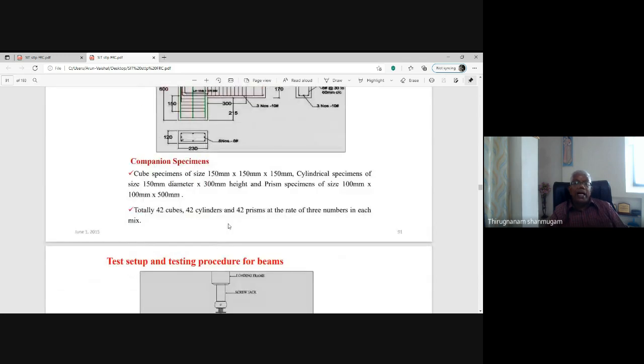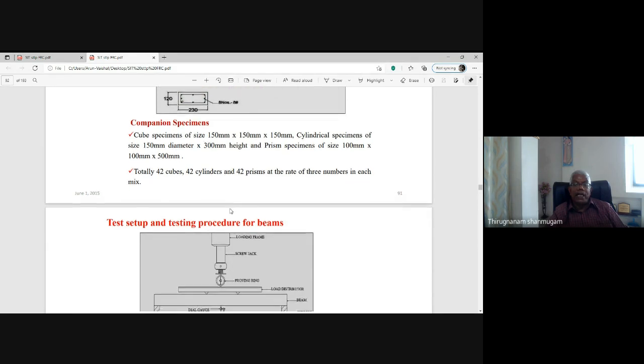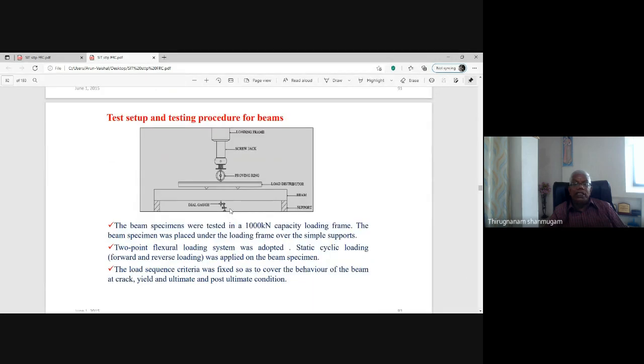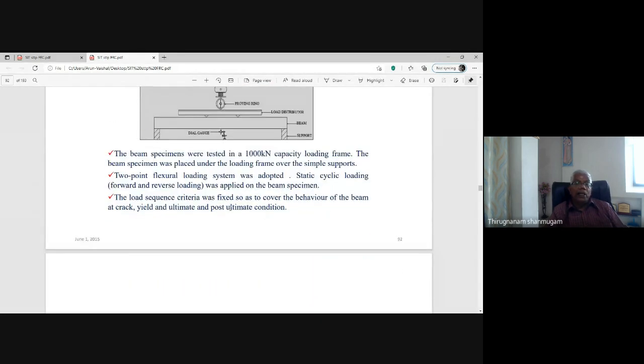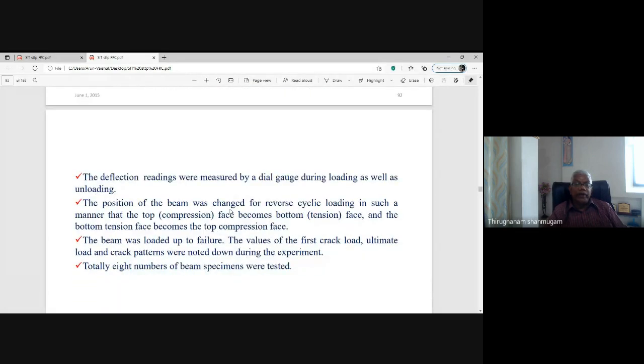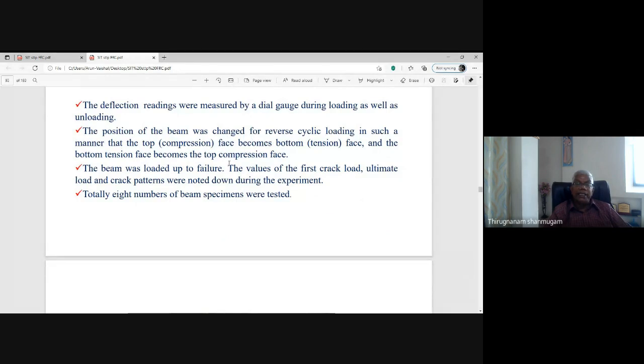Along with this beam column joint, component specimens such as cubes, cylinders, prisms, etc. have been cast and tested while testing the beam column joint. This is the test setup for the beam. It is tested under 2-point loading in a loading frame. The deflection readings were taken by a dial gauge. The position of the beam was changed for reverse cyclic loading in such a manner that we do not need a push-pull jack for this beam testing, because that involves fixity of the supports while applying the load in the upward direction. So we changed the position of the beam: the top face becomes the bottom face, and the bottom face becomes the top face.